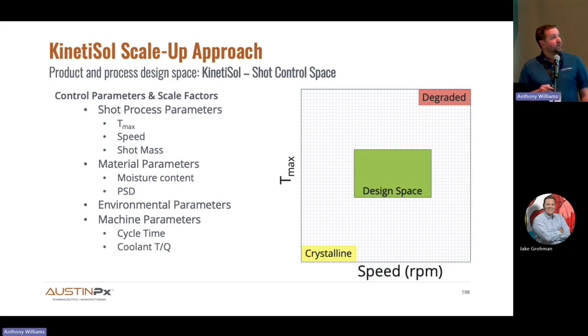We've got the maximum temperature the material may achieve, the speed, the shot mass, some material parameters, some environmental parameters, and then we have some other parameters associated with affecting that heat balance of the system. And what we see typically, and you'd see this graph, I think the Merck team wrote a really good chapter in a book that describes this space for melt extrusion.